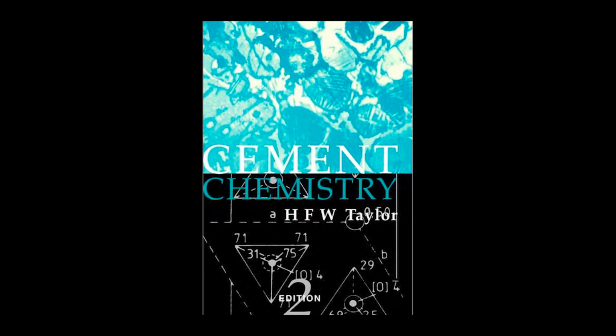In the presence of MgSO4, you form gypsum and the mineral brucite, which is magnesium hydroxide. Brucite has a very low solubility. Its formation consumes hydroxide ions, and it drastically lowers the pH of the pore solution much, much faster than sodium sulfate attack does. And that pH drop is the trigger for everything else.